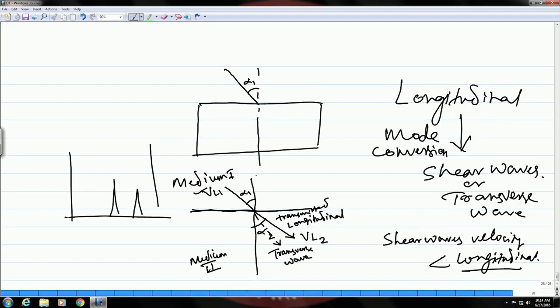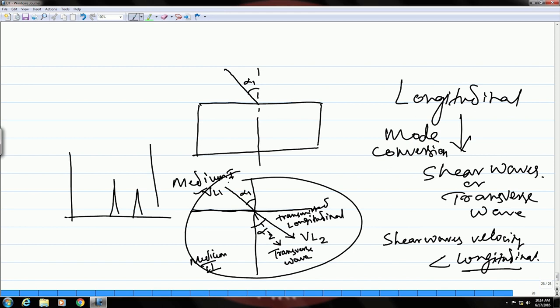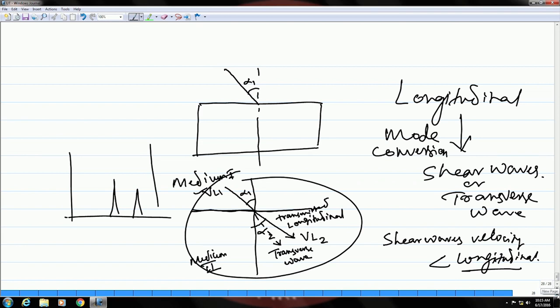That is why it is always better to have only one kind of wave going into the sample and coming back to the probe. If you want to do that in this kind of scenario, you need to exclude one of these waves. You have to exclude the longitudinal wave — the reason for that we will see in a moment. In that case you have to send it at a particular angle which will ensure that only shear waves enter the sample and the longitudinal waves will be reflected back and not transmitted to the sample. That will depend on the angle of incidence — let us find out what that incidence angle is.